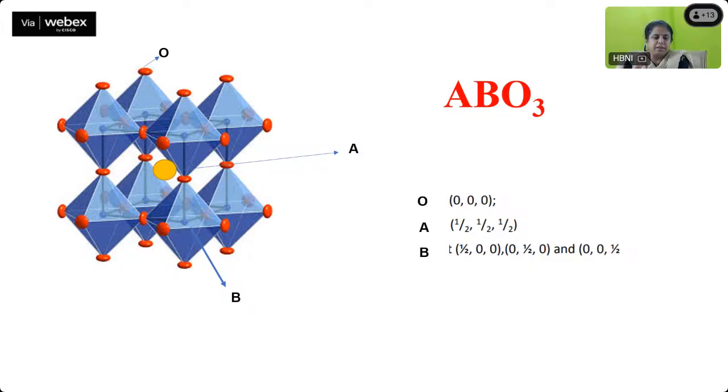So it's the ABO3 structure. If you look at it in the form of space filling polyhedra, it is BO6 polyhedra. These red buttons, which look like gems that kids see, are oxygen. Okay, the red ones are oxygen. The yellow one is A, and inside the octahedra, the blue circles are B. So three-dimensionally, it is nothing but corner sharing BO6 octahedra.